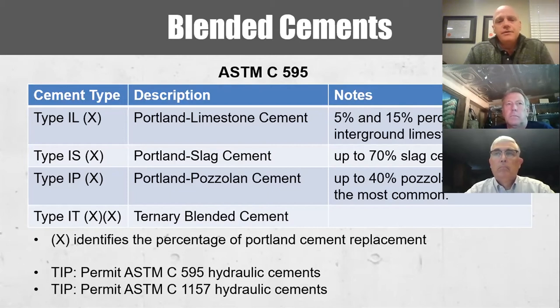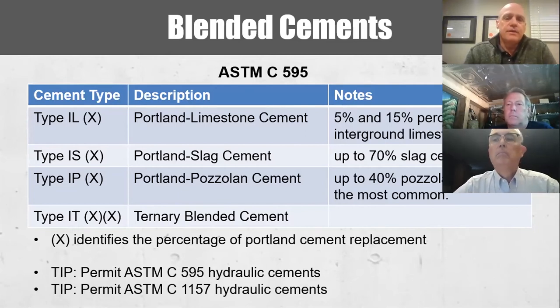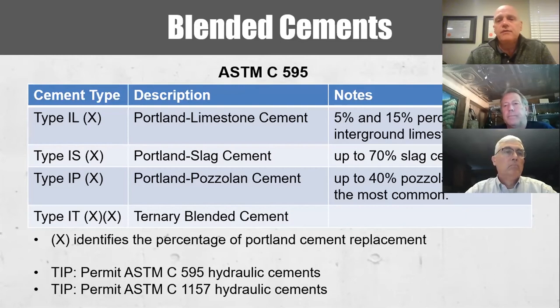And surprisingly, the performance of Portland limestone cement is almost identical to pure Portland cement. So it's really something that you need to specify and create demand for. It's still in this country slow to catch on, but really to me it's a 10% reduction in carbon footprint just by using Portland limestone cement with equal or better performance. In fact, what's great about it is that research shows that you might be able to even use more fly ash and slag in combination with PLC to reduce carbon footprint even further.